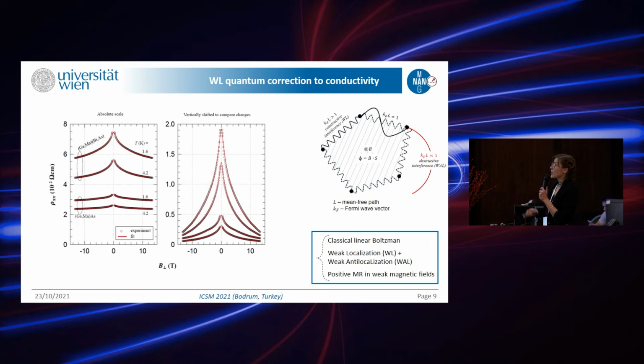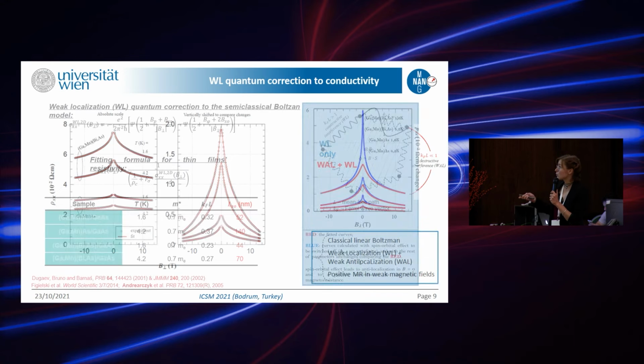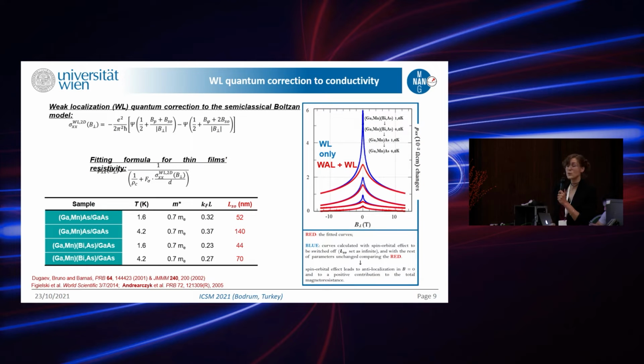And we measured this at 4.2 and 1.6 Kelvin. As you may see, both our ternary and quaternary compounds show the experimental data as open circles, while the red line is fit data. And the equation that we used to make this very nice fit is presented here. It's a weak localization correction to the semi-classical Boltzmann model.